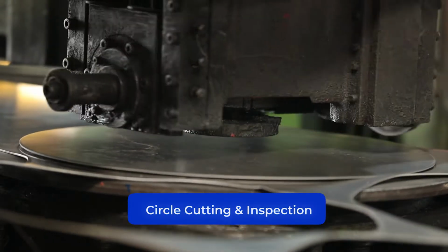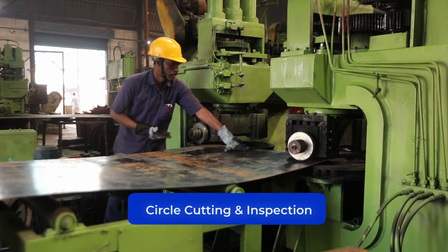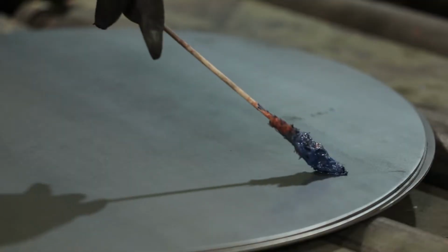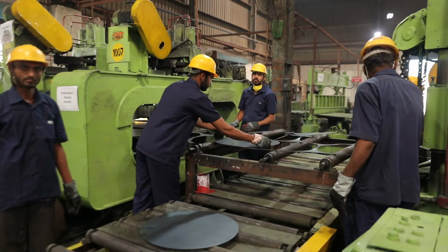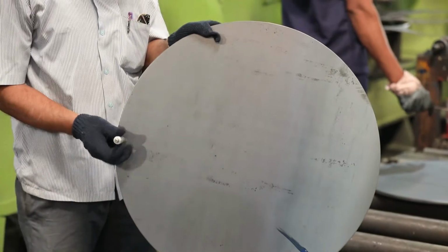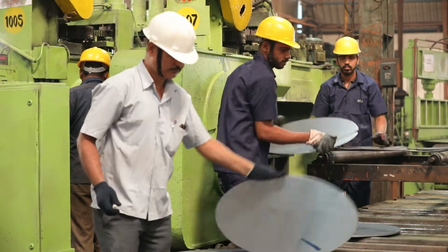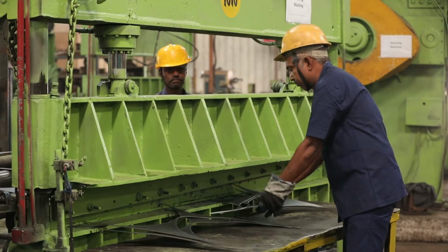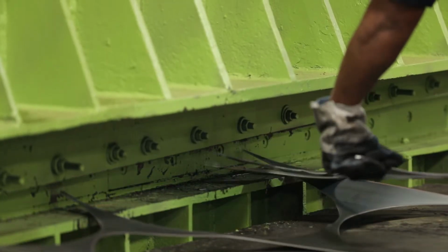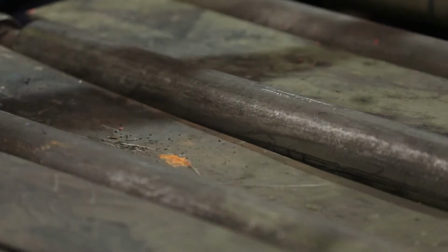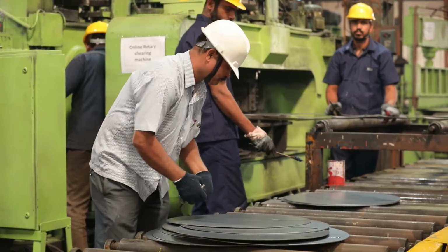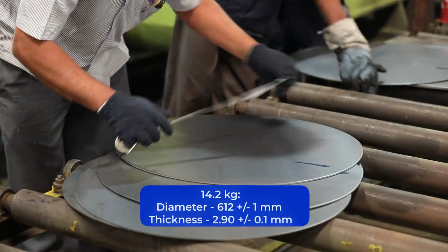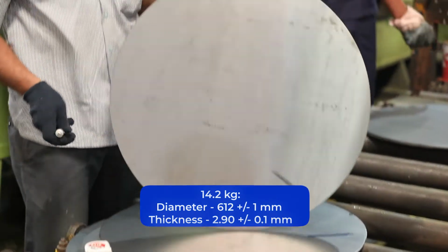Circles are cut from the coil as per the capacity of cylinders, and each circle is color-coded for identification purposes. Carry an inspection to detect the flaws in circles like burr, scratches, pits, line mark, lamination and more. Soon after, measure the dimensions of the circle in terms of thickness and diameter.